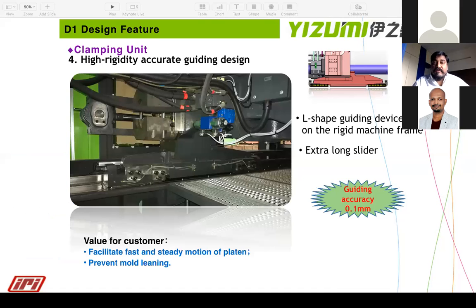Okay. And we have very high rigidity, because very important for the 2-platen machine is the platen parallelism. The platen parallelism also depends on the guide rail or the base frame, because the 2-platen moving platen is not supported by the tie bar, because it is independent from the tie bar. It is only supported by the base frame. So the slide through design is very important. Our platen design or guide design has almost 100 micron guiding accuracy. So it gives fast and steady motion of the platens, and it also prevents mold leaning or mold tilting.